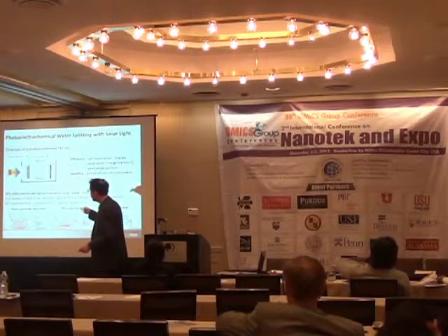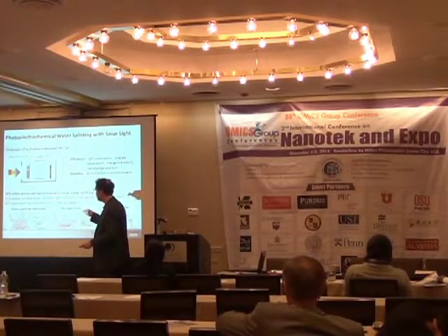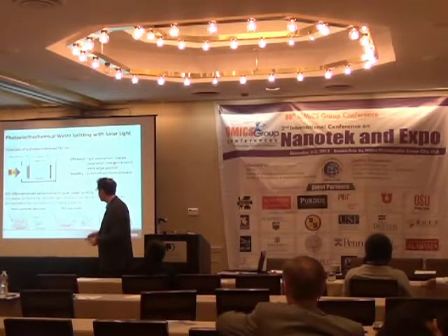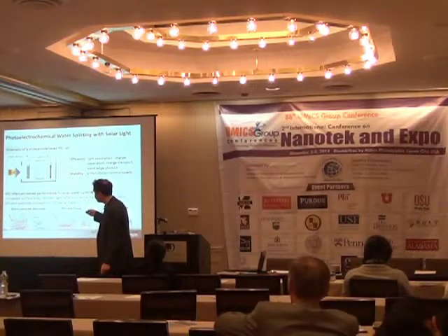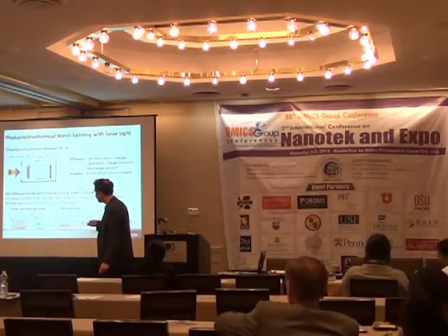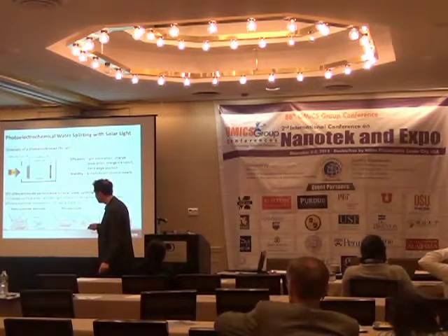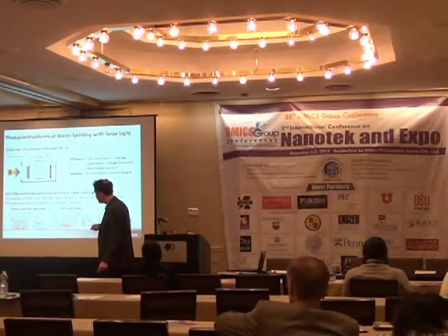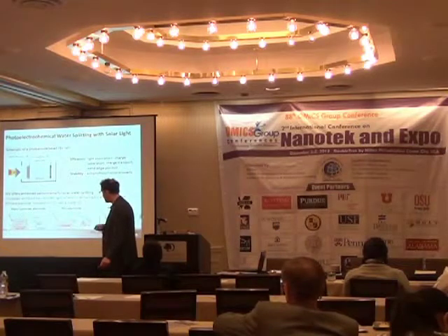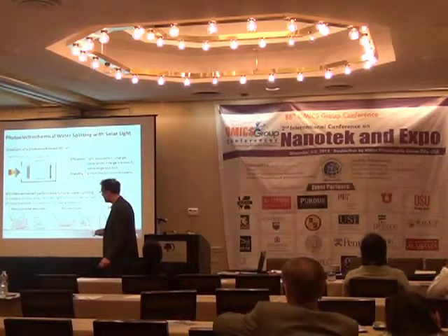Use a photocathode and an anode, or both the photocathode and the photoanode. There are plenty of configurations. So the main point here is the design of the photoanode. What is convenient is to use nanoparticles. Nanoparticles provide you with a very large surface for chemical reaction. So this is a very nice point of the nanoparticles. However, the charge transport is limited by the boundaries here, so charge transport is not very good. On the opposite, you could use a film electrode, a bulk material, single crystalline type material. In that case, the charge transport is very good, but you don't have surface for the chemical reaction.